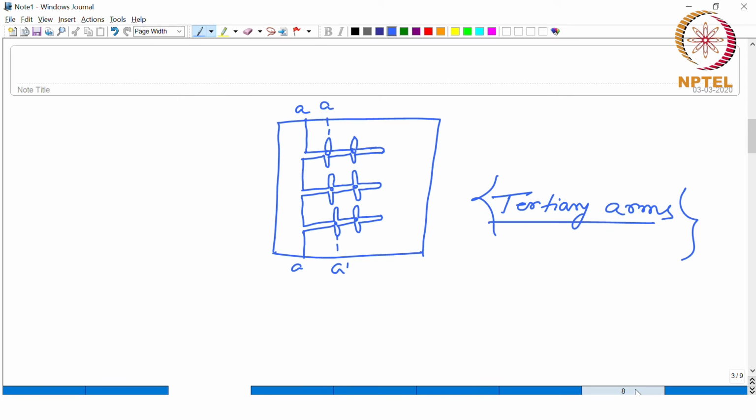Whenever those kind of conditions prevail, which leads to a liquid ahead of the solid at a temperature lower than the temperature close to the solid or close to the solid liquid interface. Okay. So, that is how the dendrites will grow as a result of this kind of temperature profile across the interface.